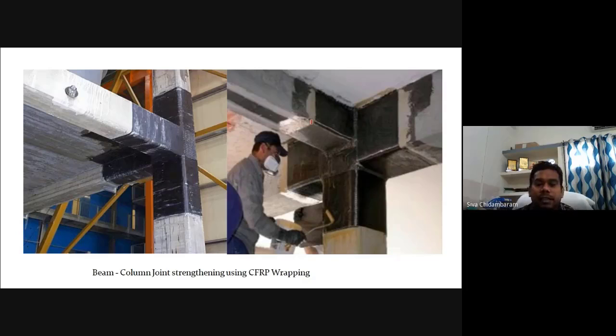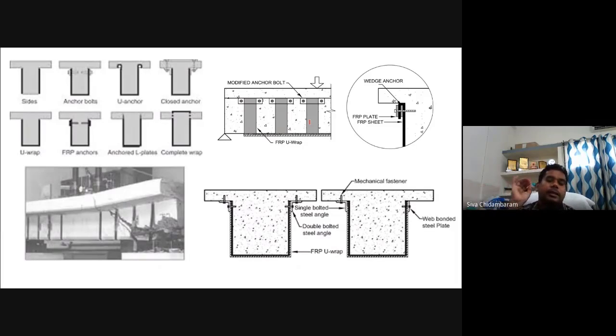So the FRP generally delaminates, because combined it is able to take the load, but we are not able to use the efficiency of the FRP to the maximum extent. So what is important in FRP wrapping is its anchorage. Similar to fiber reinforced concrete, here also end anchorage plays an important role. When you are doing U wrapping like this, exactly at this point we have to do end anchorage. You can see the end anchorage will be like this. We have to roll the FRP, insert some FRP plate or non-corrosive plate, any plate, and then it has to be anchored with the beam using some mould.